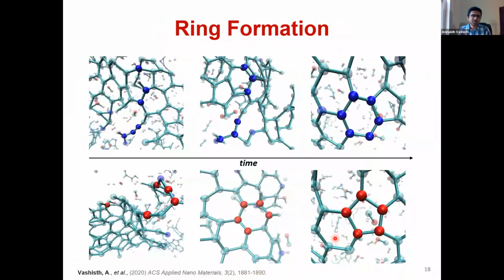So with that, we looked at laser-induced graphene, what the different formation mechanisms were, different polymers, how they behave to lasing parameters. We looked at different gases getting involved and what the yields are for different polymers. So this was also a very interesting study, which was kind of motivated by experiments, but most of the insight that we got, at least in this publication, was through simulations.